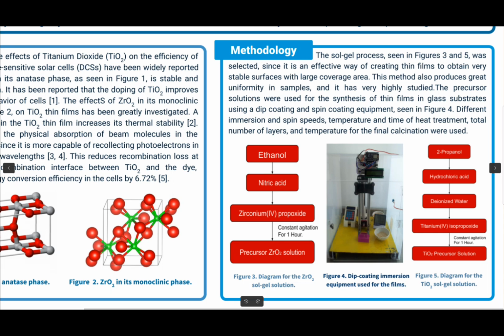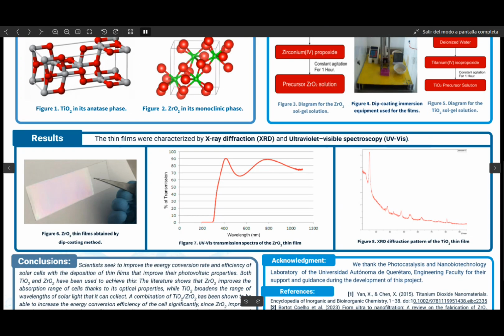After the solution was done, the thin films were placed in glass substrates using the dip coating and spin coating equipment in the lab. Figure 4 shows the immersor used. Different immersion speeds and spin speeds were used. Temperature and time of the heat treatments were varied, as well as different total numbers of layers and temperatures for the final calcination process. Figure 6 is a picture of the zirconium dioxide thin film obtained in the lab.